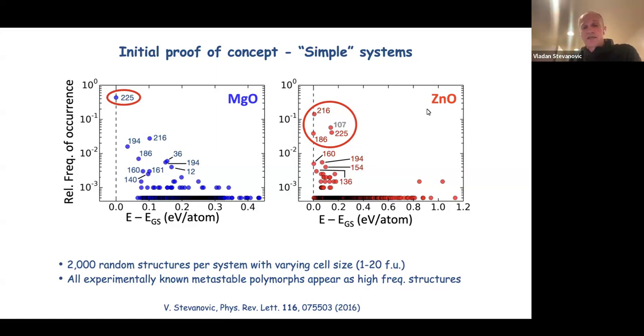So this was a very nice initial proof of concept, or validation of our initial hypothesis. Since then, we have tested this on around 30-ish systems, between 30 and 40 actually. And whenever the system is not so complex that we cannot converge the random sampling, the result is always the same. So in my mind, this hypothesis has been well validated by now. This paper was published almost 10 years ago.